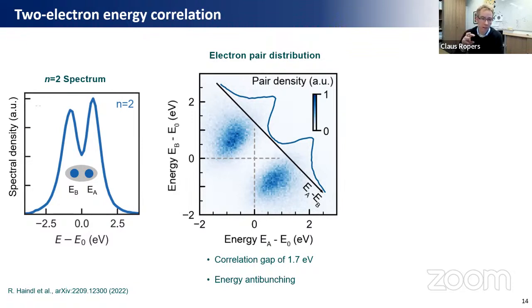So if you only look at the 2 electron events, you can plot the distribution of events as a function of the energy of one of the electrons versus the energy of the other electron. Yeah? So you have here like a 2-dimensional correlation plot. And what you see is quite a strong correlation gap, such that you don't find electrons at the same energy. One of the electrons is always in this lobe here, the other electron is always in this lobe. Yeah? So there's a strong anti-correlation in energy, no electrons found at the same energy. This is a clear proof, basically, of the strong Coulomb interaction of these two electrons.